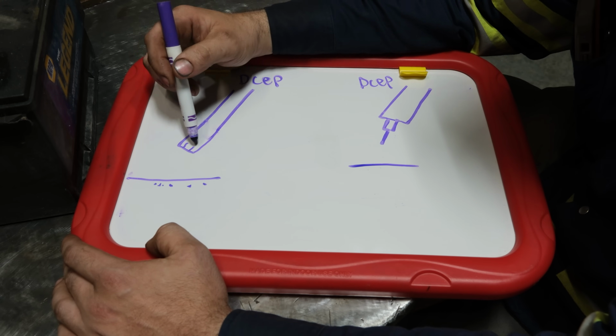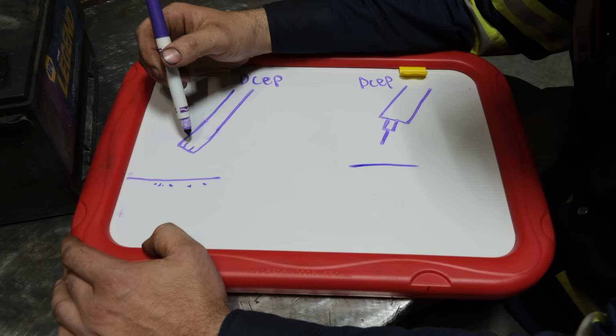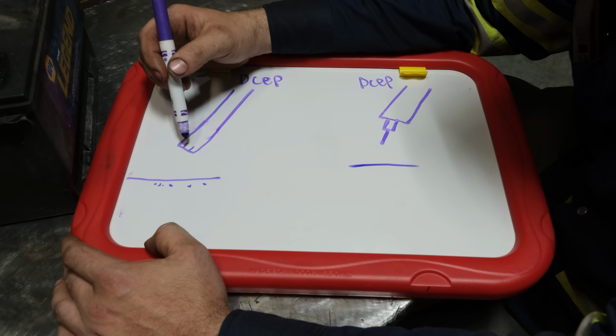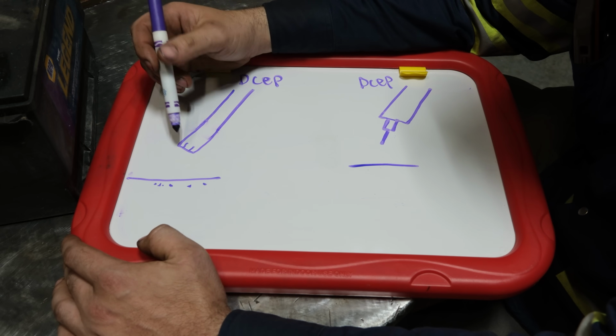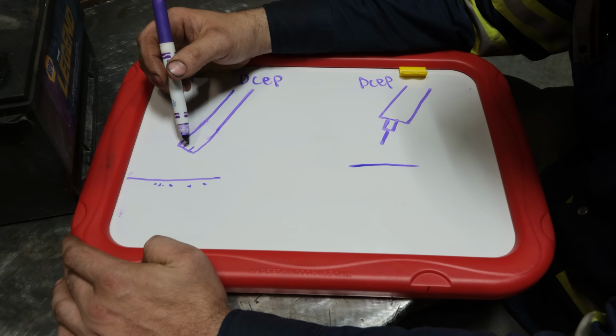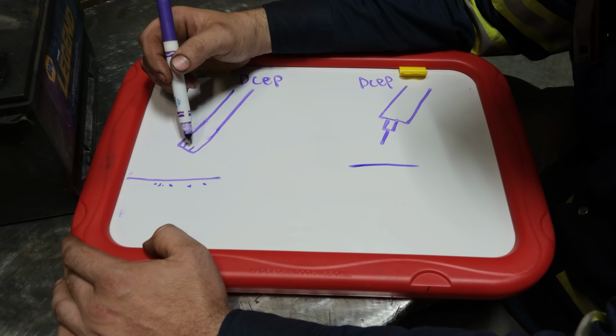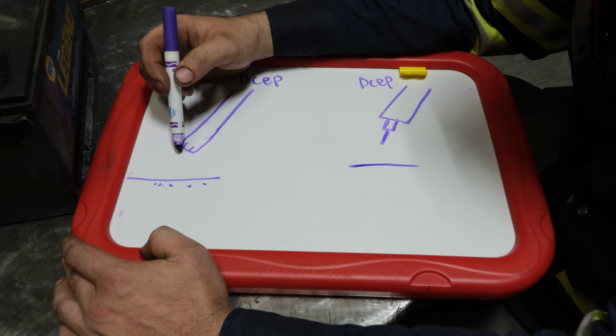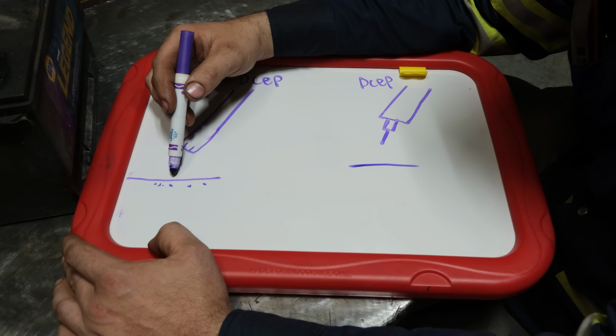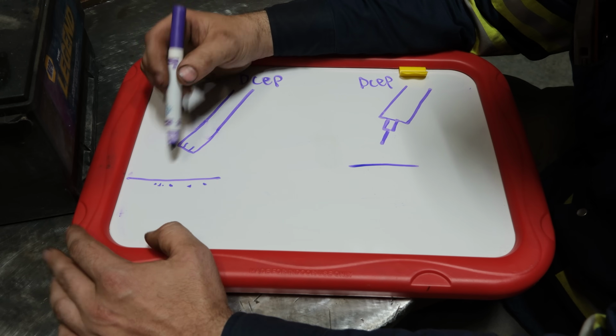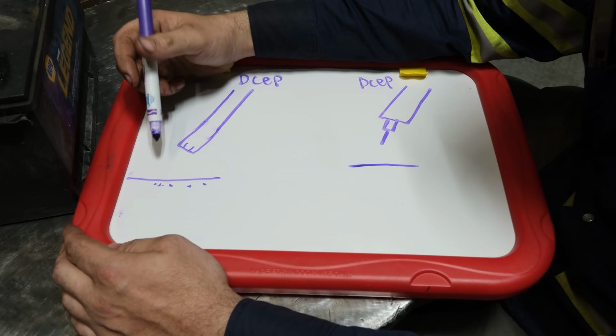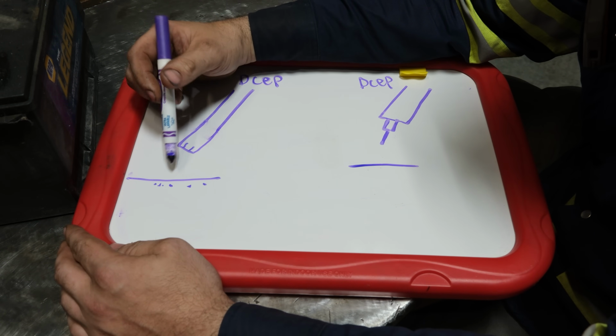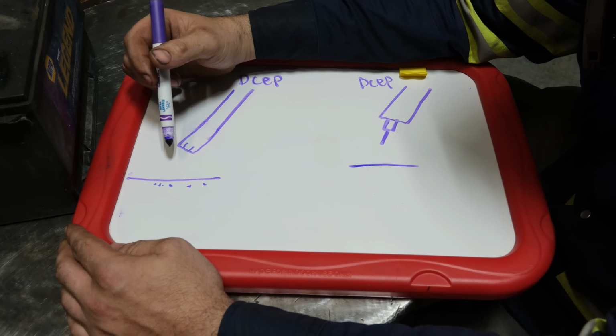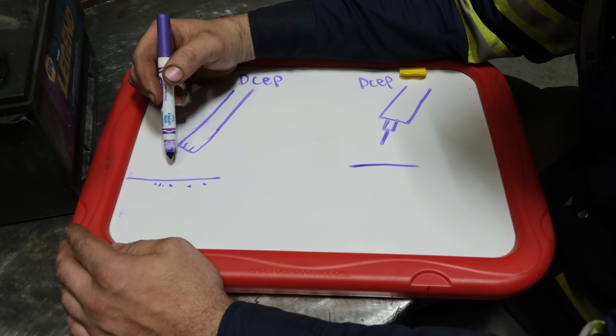The second thing it does, that impact force on the tip of the rod on stick welding, gets that rod super hot. And you guys got to remember, with stick welding, you're running a 1/8 inch, 3.2 millimeter rod, or a 3/32 rod very typically, and that is a very big wire. By running EP, it gets that wire tip really hot, and more or less balls of metal will jump across onto the plate, and due to surface tension, much like two water drops getting close to one another and joining, that molten metal from the rod tip hitting that molten pool on the metal will join it, and you'll have metal deposition.